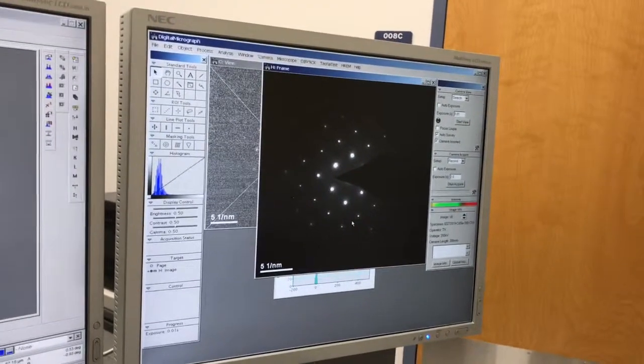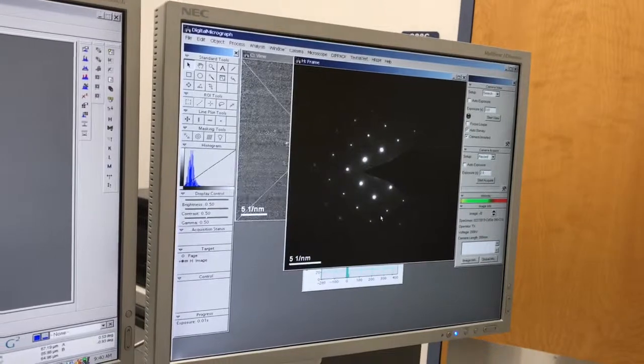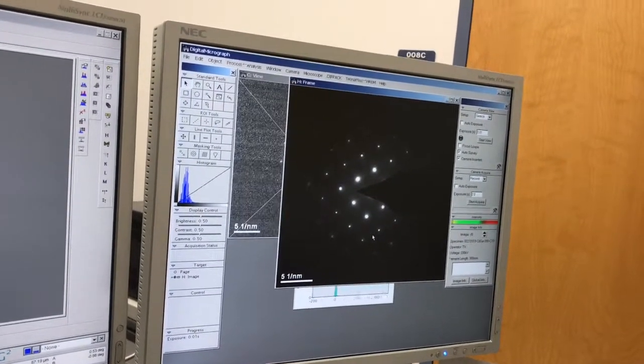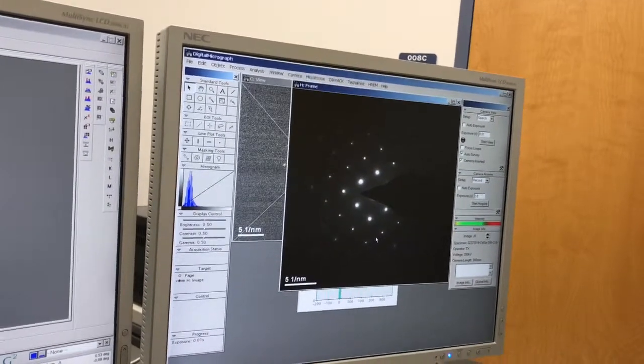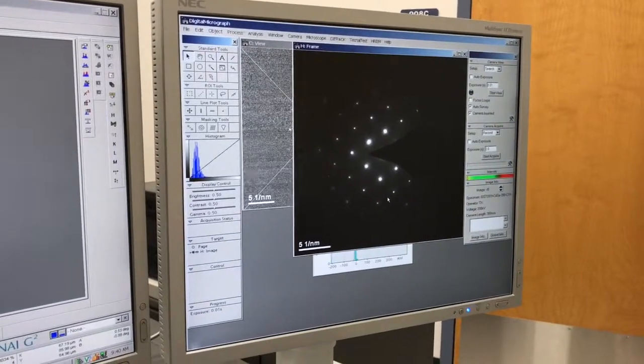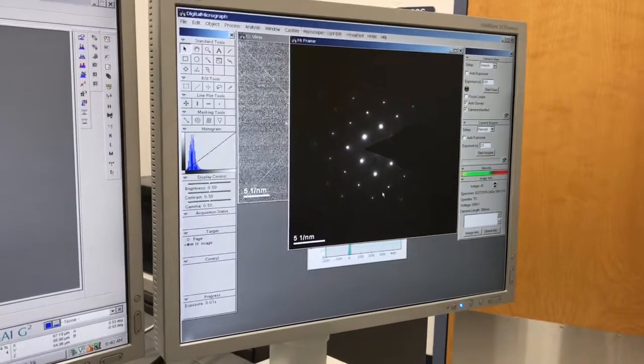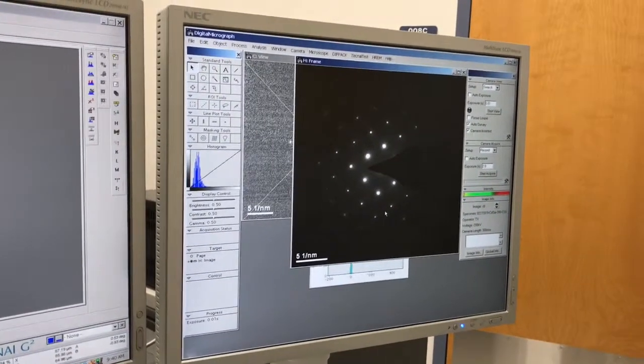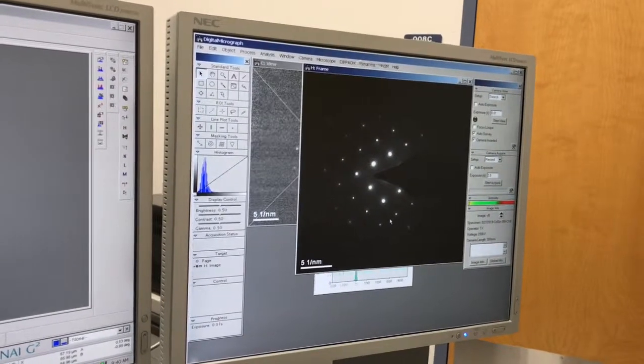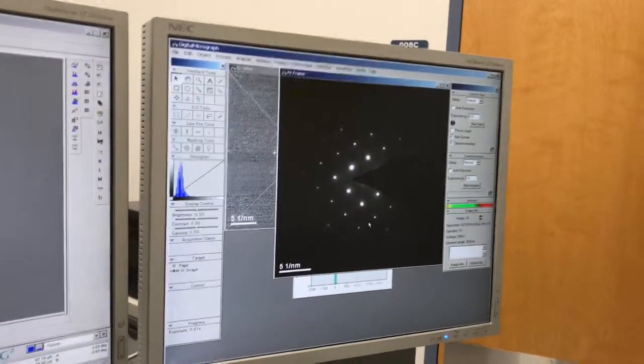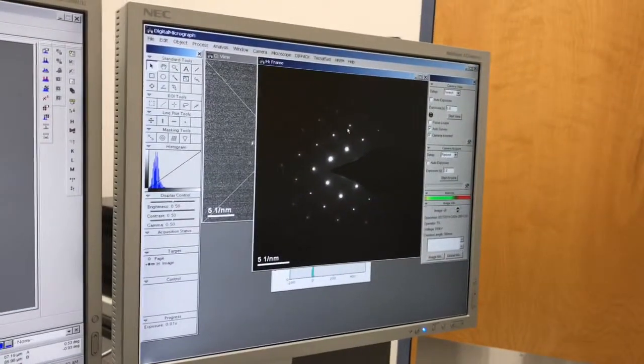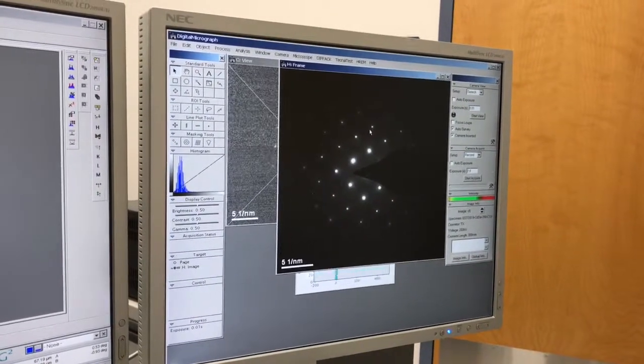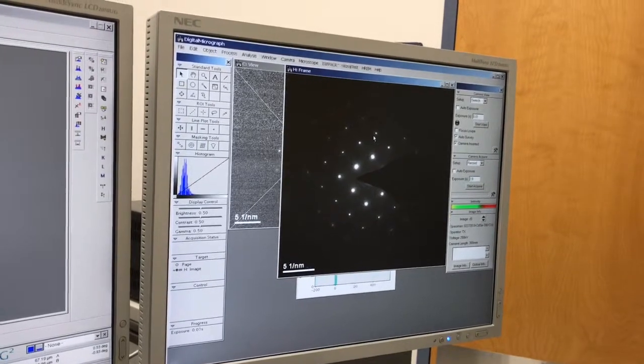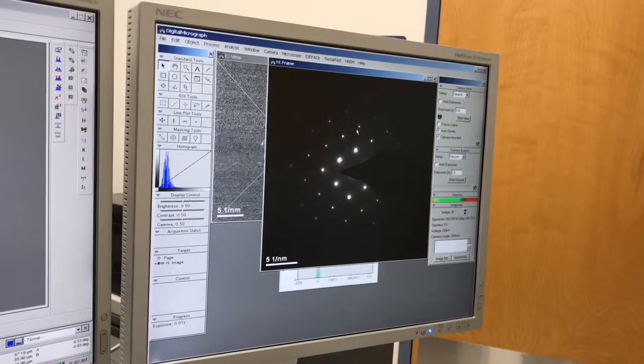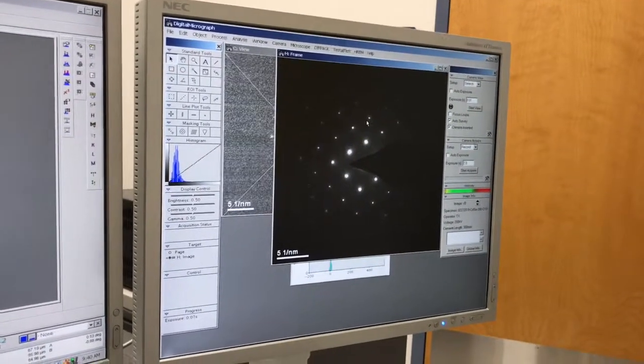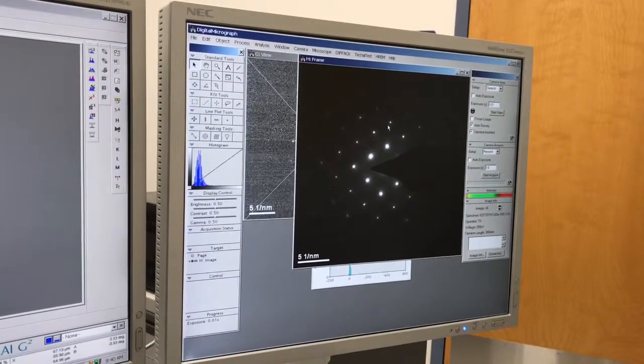So the same basic idea applies when you're collecting diffraction patterns. Longer is better in terms of signal to noise, but you have to balance that against potentially damaging the camera. Unlike when collecting an actual image, we're not really concerned with things like drift, because this isn't a high resolution image. We're looking at a really small field of view. This is a diffraction pattern. So if the sample moves a few nanometers within the exposure time, that really isn't going to have a large impact on this pattern. So we can afford to use something a little bit longer. I wouldn't go longer than 2 seconds on this. If I go to 3, for example, I'm probably going to exceed the dynamic range, and that would be a problem. So that's a basic synopsis of how to choose exposure times when you're recording data, both images and diffraction patterns.